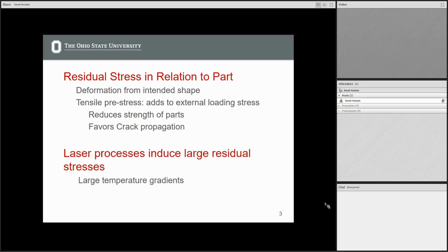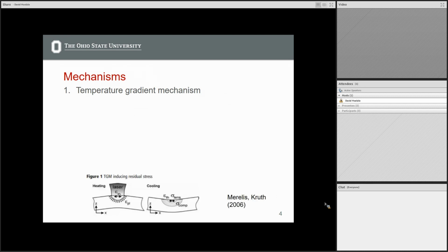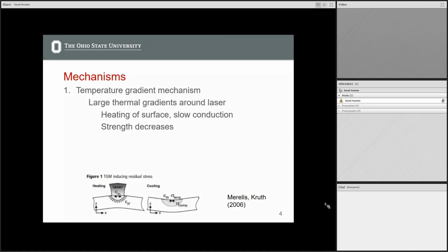So it was well known before this paper that laser processes do apply a residual stress to your part itself. In fact, these large temperature gradients were used for a process known as laser bending, which is using the laser to actually bend sheet metal to a required shape. So the mechanisms that they talk about that actually apply this pre-stress, there were two. We have the temperature gradient mechanism, which they describe using this figure here. The way this mechanism works is that a large thermal gradient begins to develop around the laser as you have a lot of energy heating the surface, but relatively slow conduction of heat through the part. So that's going to cause a decrease in strength of the part in that area. So when you're heating, you're going to get a bend away from the laser, and then once that material begins to cool, once you remove the laser source, you're going to begin to get a bend towards the laser direction.